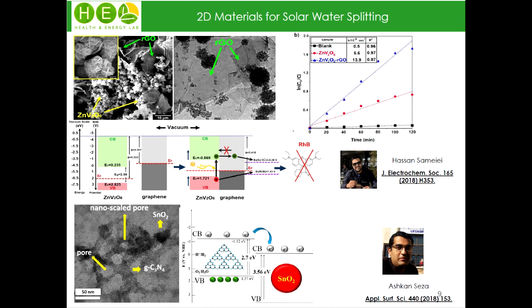Using DFT calculation, we realized that the band alignment at the interface of the semiconductor material and graphene is beneficial for charge separation in the zinc vanadium oxide and suppresses recombination. Also, such a porous and high surface host could increase the total available surface area between the dye, the solvent, and the photoactive material.